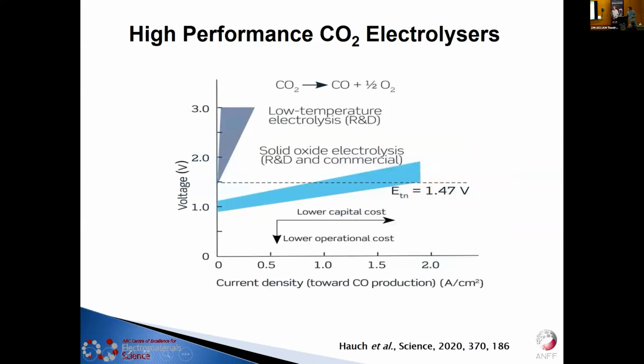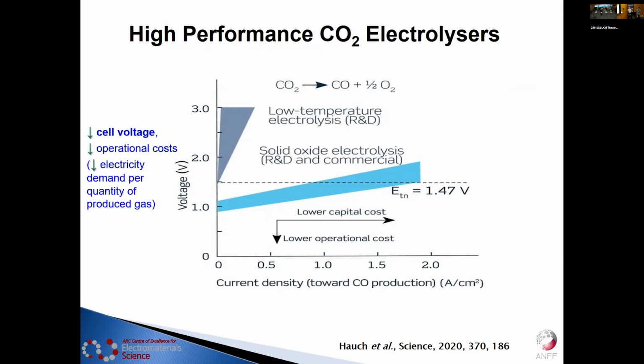So let's look at what we actually need to have as a benchmark. The benchmark for the CO2 electrolyzer is actually solid oxide electrolysis. In this case, we have quite a regular product, like carbon dioxide to carbon monoxide. And this is of course at high temperature, but still a good benchmark. And they really get a very low slope here. So what's actually required here is a low cell voltage operating at a high current density.